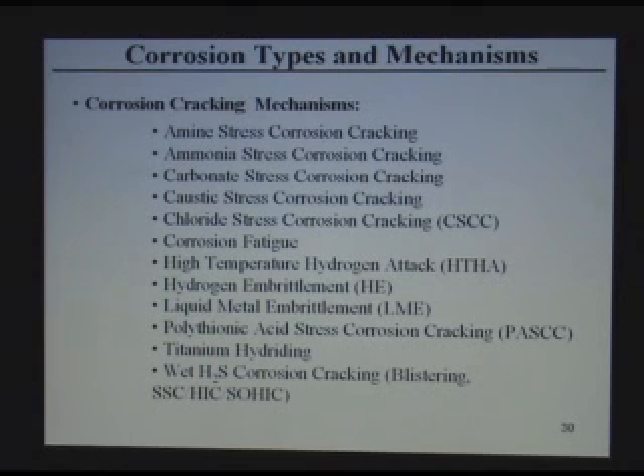Hydrogen embrittlement. As hydrogen diffuses at high temperature inside the metal, it gets trapped inside the metal, and the metal loses ductility and becomes brittle. So unless you outgas the hydrogen from the steel before you shut down, because when the equipment is hot, hydrogen is inside the metal. If you cool fast and you don't get rid of the hydrogen trapped inside the metal, it can crack the steel.